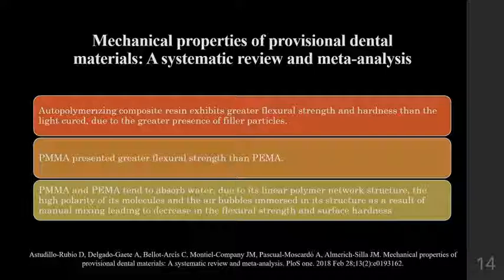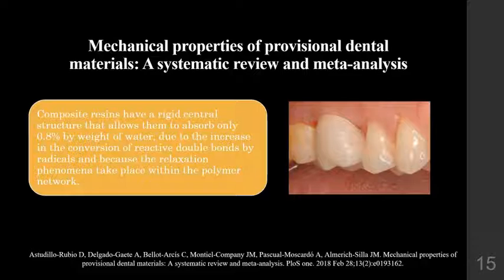Auto-polymerizing composite resin exhibits greater flexural strength and hardness compared to light-cure, due to the presence of greater filler particles. Polymethyl methacrylate presented greater flexural strength when compared to polyethyl methacrylate. PMMA and PEMA tend to absorb water due to their linear polymer network structure, which decreases flexural strength and surface hardness. Composite resins have a rigid central structure that allows them to absorb only 0.8% by weight of water.